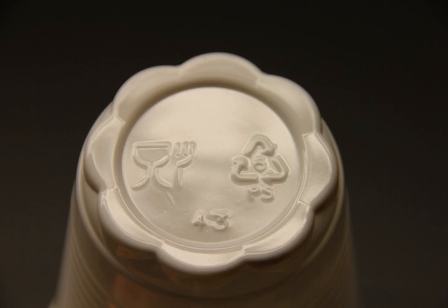Extruded polystyrene material is also used in crafts and model building, in particular architectural models. Because of the extrusion manufacturing process, XPS does not require facers to maintain its thermal or physical property performance. Thus, it makes a more uniform substitute for corrugated cardboard. Thermal conductivity varies between 0.029 and 0.039 W/(m·K), depending on bearing strength and density, and the average value is approximately 0.035 W/(m·K). Water vapor diffusion resistance (μ) of XPS is around 80 to 250.